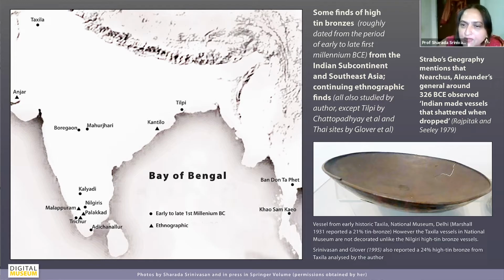Now, you're looking here also at an early historic vessel in Taxila. So obviously, at some point, with the Hellenistic influence and so on, you do see perhaps that these started being made there as well. But they are not elaborately decorated in the way the Nilgiri high-tin bronze vessels are. I also studied a fragment of a 24% high-tin bronze from Taxila, which was given to me by Ian Glover, which was also from Pakistan. So one can see that this tradition was spread over the subcontinent and still continuing in many places, I would say, at least till quite recently.